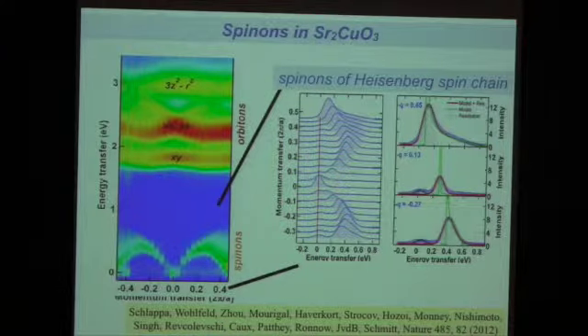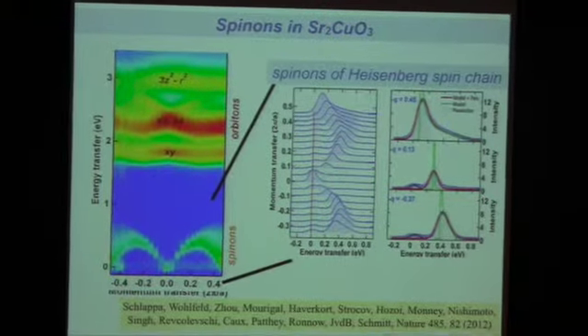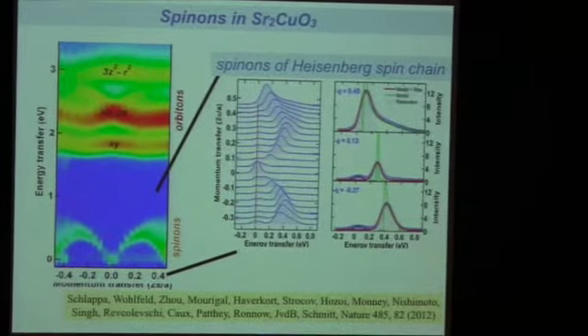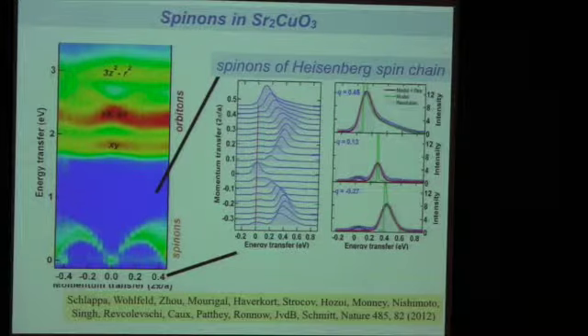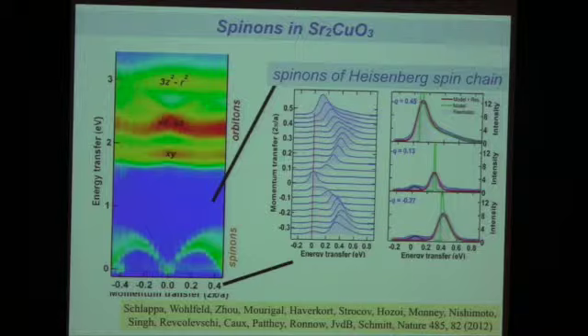So neutron scattering is best when you have the highest fluxes, if you had thermal neutrons that have an energy of 300 K, 25 millielectron volt, that's it. Here you see that the spectrum goes up to 500 millielectron volt. So the thermal neutron doesn't have enough energy to produce that kind of excitation. You would have to go to neutrons with higher energy, which they tell me is possible, but that's experimentally much more difficult. Fluxes go down, essentially.